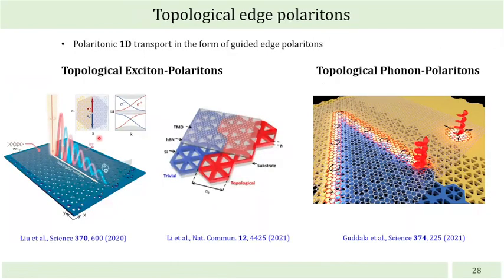So still using the abrupt mass inversion profile, recent papers reported observation of guided topological helical polaritons, which originate from coupling of the structured modes in metasurfaces with excitons or phonons in two-dimensional van der Waals materials. This may lead to a new form of polaritonic transport enriched by functionalities such as bending around sharp corners.